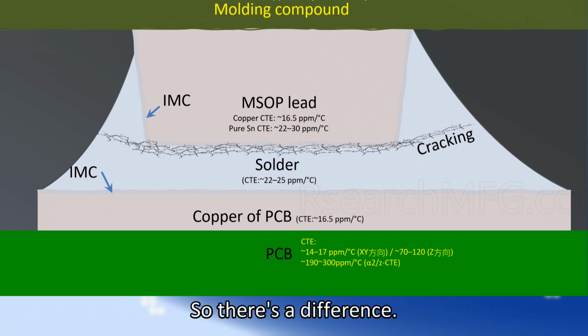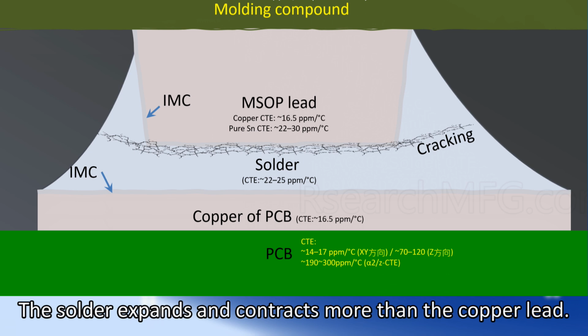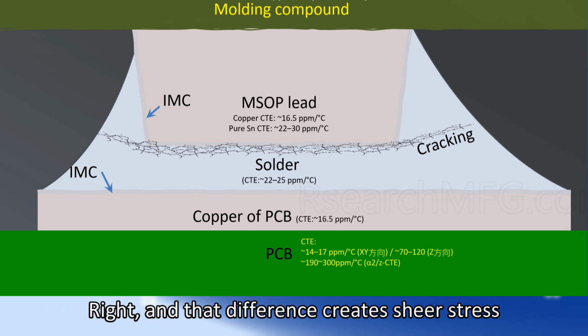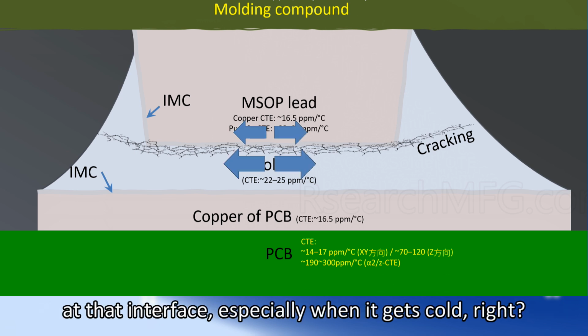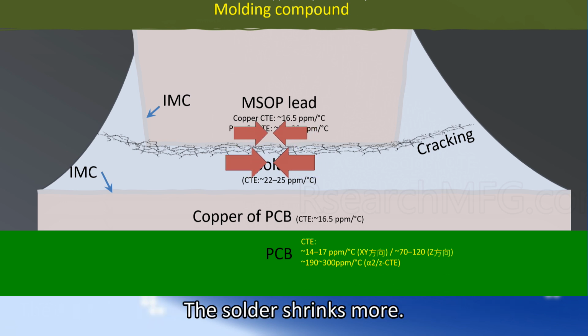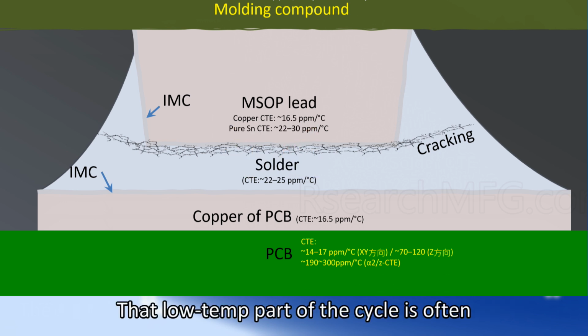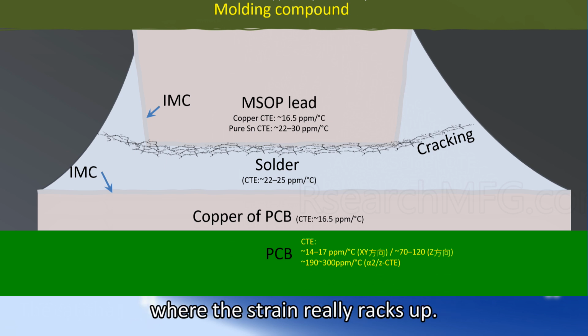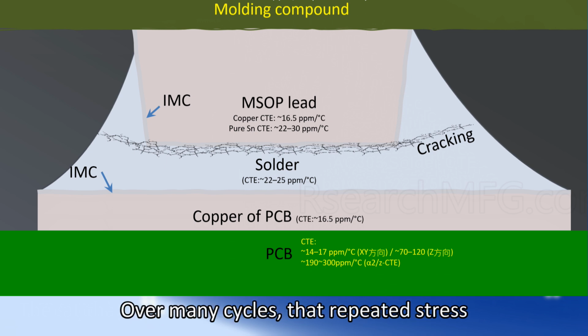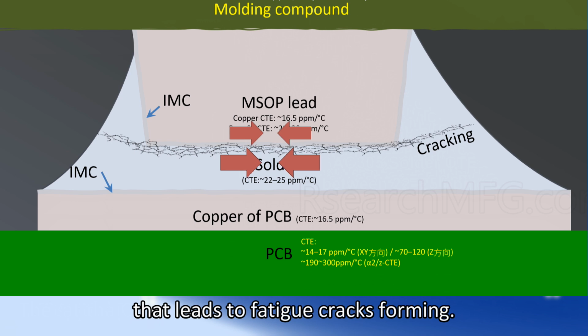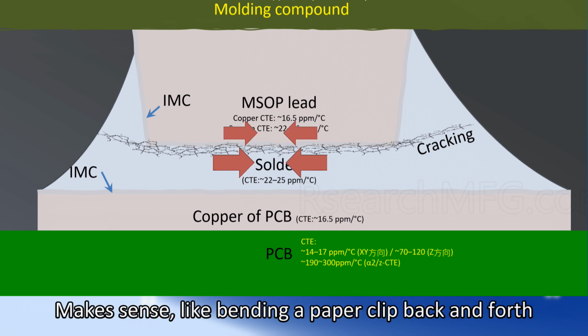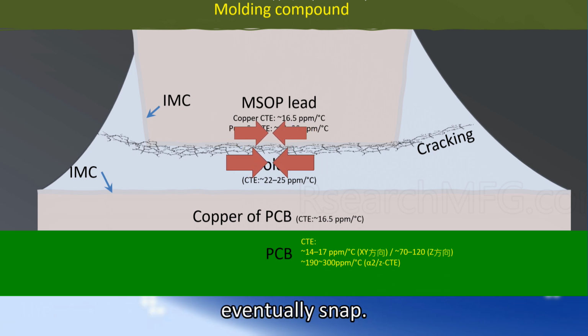So there's a difference. The solder expands and contracts more than the copper lead. Right, and that difference creates shear stress at that interface, especially when it gets cold, right? The solder shrinks more. Exactly. That low temp part of the cycle is often where the strain really racks up. Over many cycles, that repeated stress leads to fatigue cracks forming. Makes sense, like bending a paper clip back and forth, eventually it snaps.